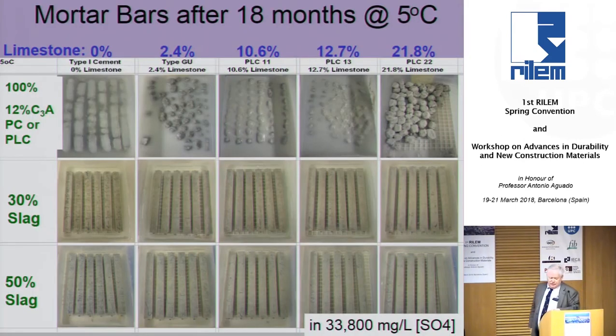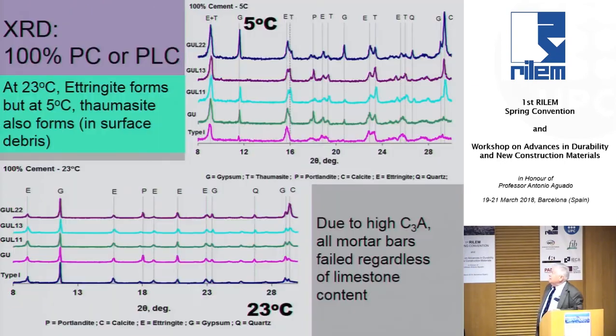And this just shows some of our early experiments with different amounts of slag. This is a high C3A, so this is a typical high C3A Portland cement, and this is the same cement replaced by slag, and then different amounts of interground limestone in the system. Now we only allow 15%, but we did one deliberately at 22%, and you can see the damage. And some of this has to do with Thaumasite, although as we found later, it happens after the fact. And if you put slag in, you don't have any problem after 18 months.